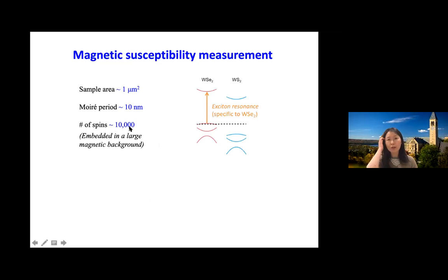So what we try to do is to use optics to study it, because those transition metal dichalcogenide semiconductors have very strong exciton resonance. So optics is very location specific. So you can probe an exact layer of this material. And I mentioned optical selection rules. So in those materials, the K and the K prime valley couple exclusively to left-handed or right-handed light.